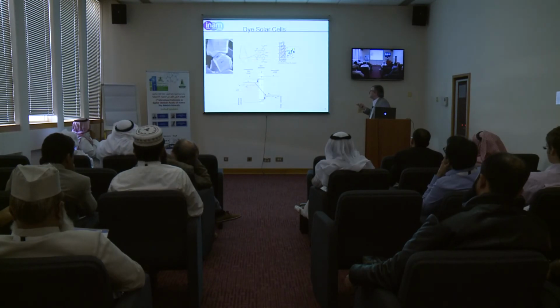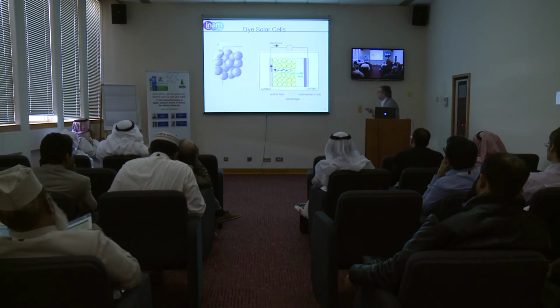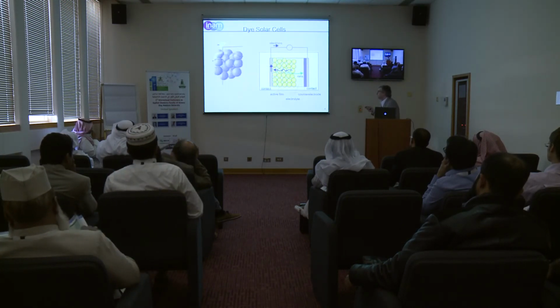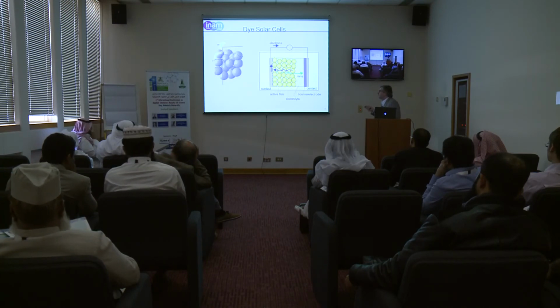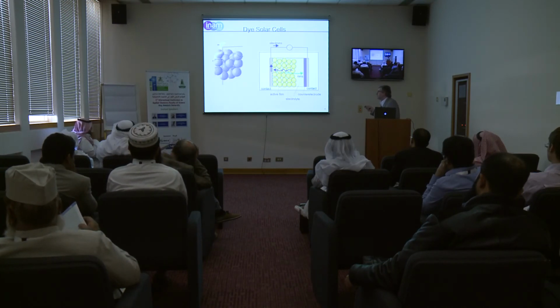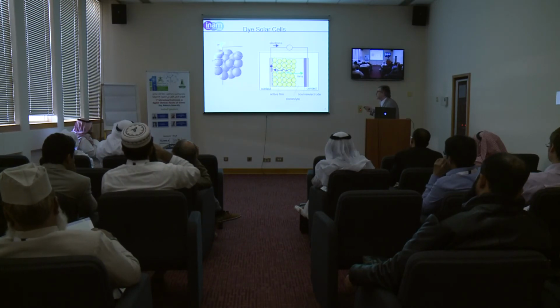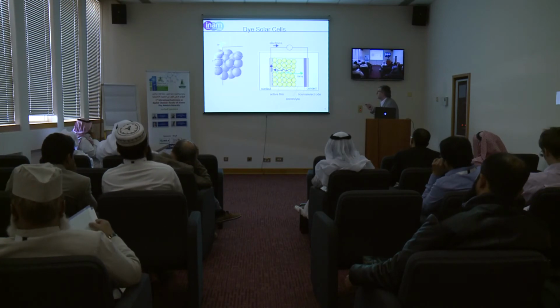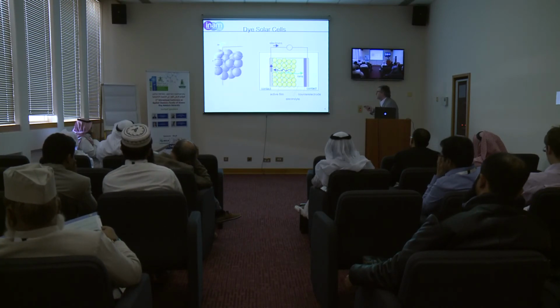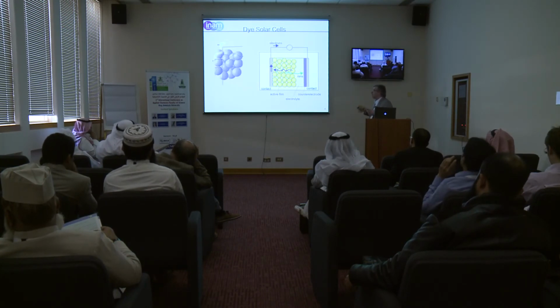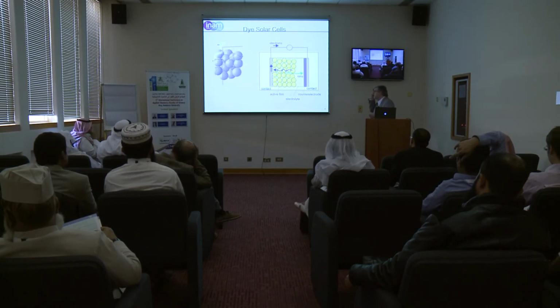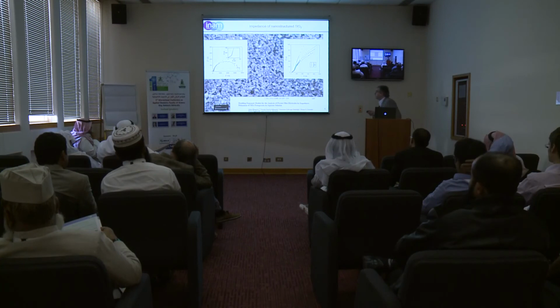When you use this sensitizer, it has a very small extinction coefficient, so you need a bigger area. The way to have bigger areas is to use a porous structure, as represented here, so you can collect electrons all the way. Electrons collected far away from the contact will have to travel to the contact. Then they will go around and meet here with an oxidized ion. So this is the closing of the circuit. So we have very interesting phenomena of the transport of electrons in disordered materials, and this has been widely studied by us and by many other people.